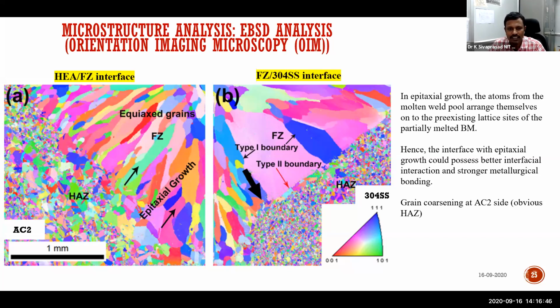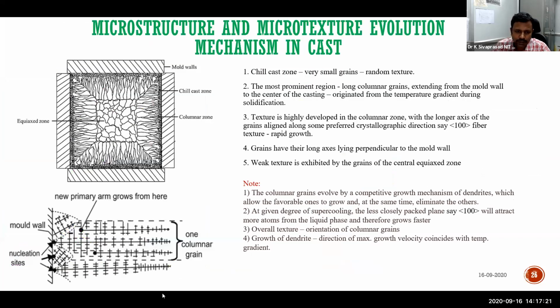You can see epitaxially grown crystals, and almost the same magnification was taken. On the left side you can see a very fine dendritic structure, whereas on the right side, the steel side, we have seen a very coarse dendritic structure. The coarse dendritic structure is very common wherever type 2 boundaries form. In some systems it is essential to grow wider dendrites so that the system will have a softer structure, so it will not be brittle, embrittled or hardened. There is a typical growth structure, and normally in casting it is very clearly explained. Here also it is nothing but a localized casting, so you can see decent microstructures similar to those of a cast material.